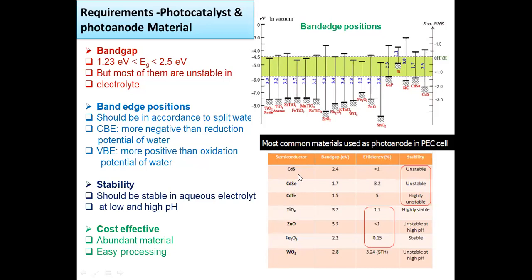Here in this table, what we should look at is the band gap of the material and the stability, because this stability tells us what the challenge is in nature. Nature has given us a few systems which are perfect with respect to the band gap, but not with respect to stability. That is the case found in CdS, cadmium sulfide, selenide, telluride. So these systems have very suitable band gaps, which make them suitable for water splitting by sunlight. But if you try to implement this, it takes no time to degrade these photocatalysts. So that is a challenge.